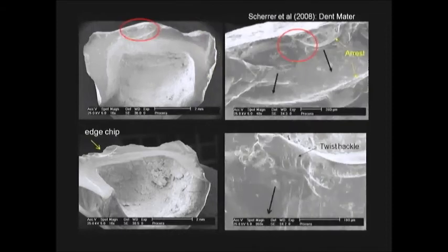What is this? I told you before, there is a arrest line, and the starting point of a chip or a damage is on the concave side of an arrest line. So this time we're talking the occlusal surface. An arrest line, an arrest line, an arrest line. And at higher magnification, twist hackle, everything moves from top downwards. But